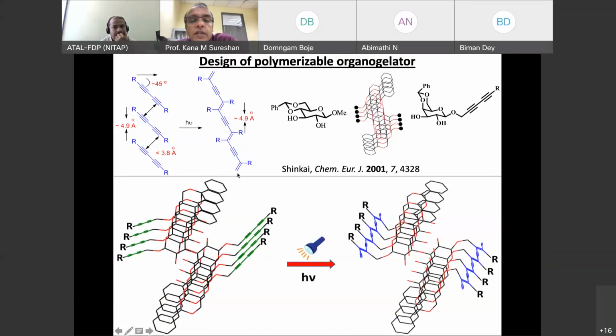Now, if we have this conducting polymer, yes, that's good for static charge dissipation. Now, how do we plan this one? What is the challenge here? How do we align this monomer in solution? It's impossible. In crystal it's possible, but we don't want to do it in crystal. We want to do it in gel. Gel is also possible, so that's what we have shown here. This is Shinkai's gel, a glucose-based gel. He has also shown that when you crystallize this one, you can see the methyl, which is shown as this bold, stacks one over the other.